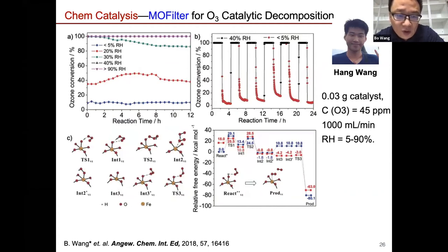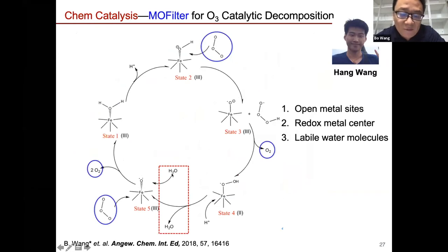Interestingly, when we use this MOF MIL-100, what we are seeing here is that it's directly related to the humidity level. When the relative humidity level goes all the way down to zero, the ozone conversion is really low. So it's very different from other metal oxide behavior. We did a little bit of calculation on this, and we realized this whole process is facilitated or enhanced by water uptake and water release on this iron center. So it's actually a very smooth process with water. Without water, the ozone cannot be easily converted to oxygen in this case. So MOF in this case actually behaves very differently.